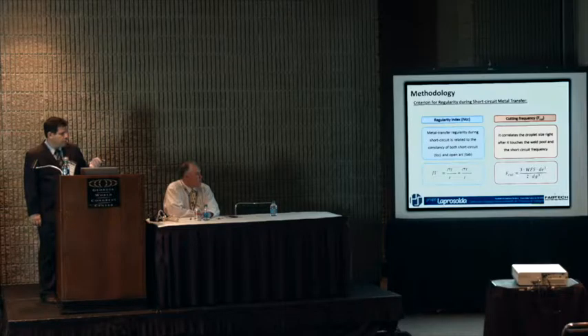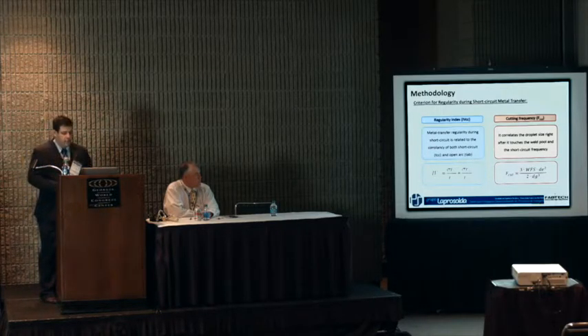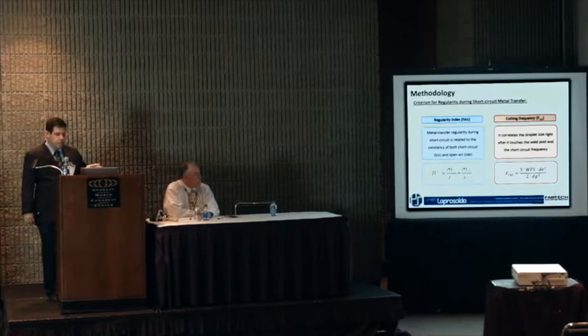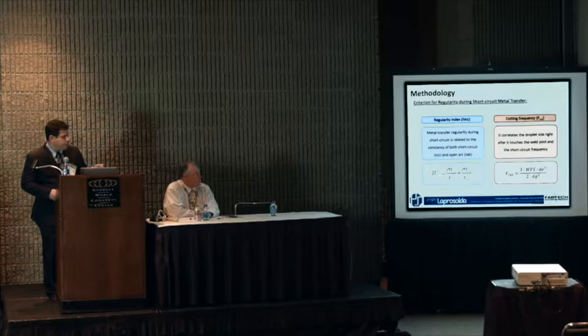We have to establish a frequency of metal transfer, a cut frequency, below which you don't consider the metal transfer, because when we are at short circuit metal transfer, if we increase the voltage, we end up with globular metal transfer. And in the limit, globular metal transfer has zero time of short circuit. So zero means zero deviation. So you may consider the index perfect for globular transfer.